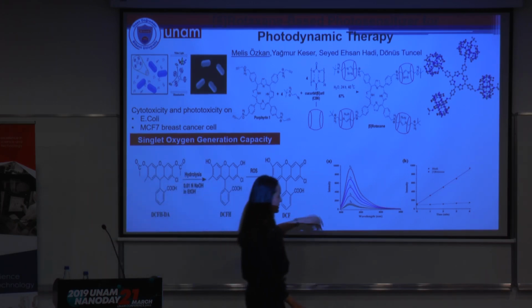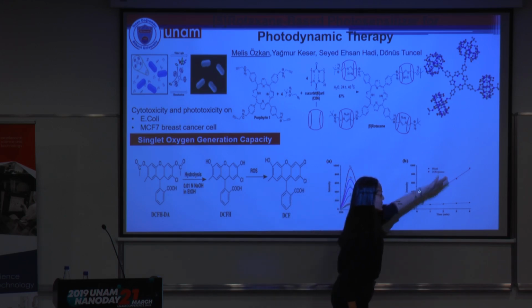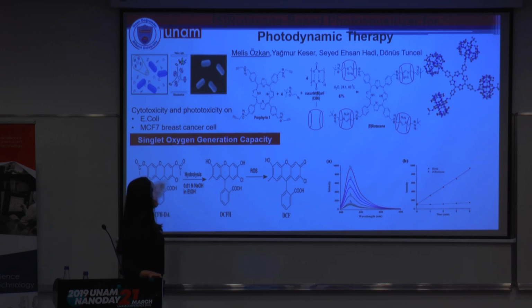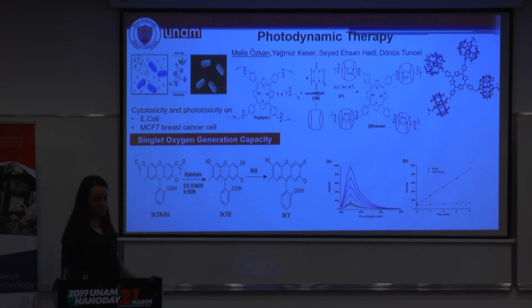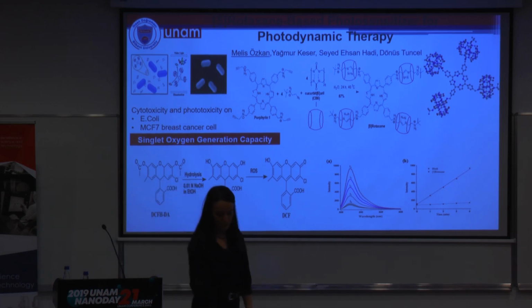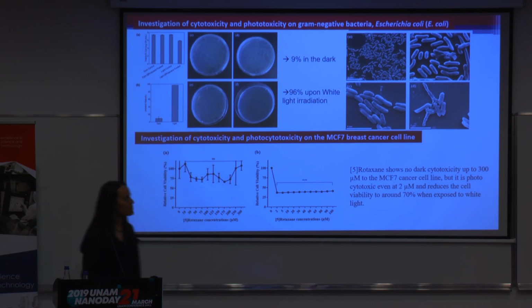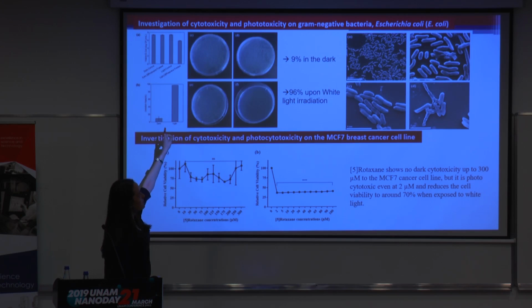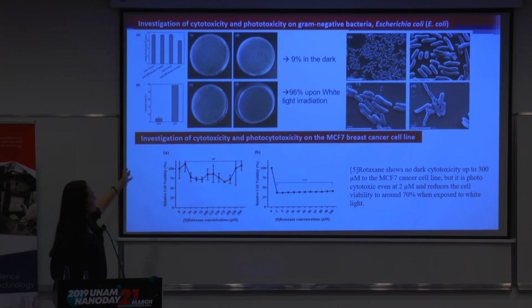As you can see here, this is the singlet oxygen generation capacity of that molecule. It turns triplet oxygen into singlet oxygen, and we used that ability in photodynamic therapy, first on E. coli, a gram-negative bacteria. Once we shine white light, in the presence of light, we will see singlet oxygen generation. Figure C and D, the dark experiment, C is control, D is dark. We don't see any remarkable effect in the dark, just 9% inhibition, but in the light we see a huge amount of inhibition in the white light.